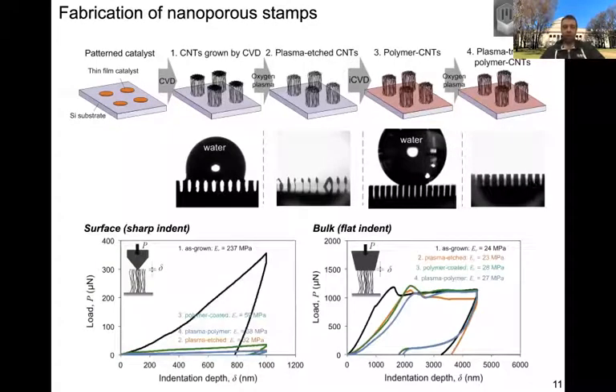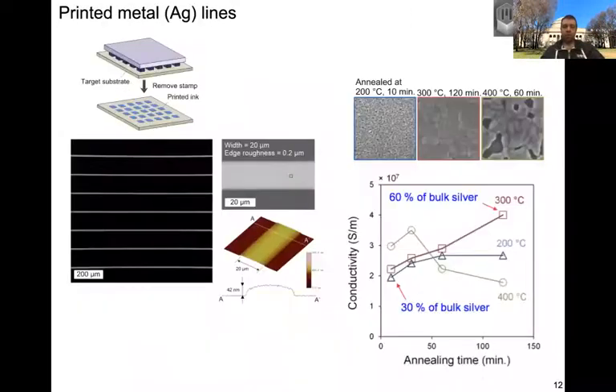And that plasma etching step, I'll just say quickly, is also important because it removes what we call a crust layer of higher density CNTs from the top and enables the surface of the pillar to be the same mechanics as the bulk of the pillar, and that's important to have the compliance to get good contact between the stamp and the substrate. And compliance is important to get all the CNTs to touch the surface and therefore transfer the ink as an array of little tips, and also important over larger dimensions to accommodate roughness of the substrate.